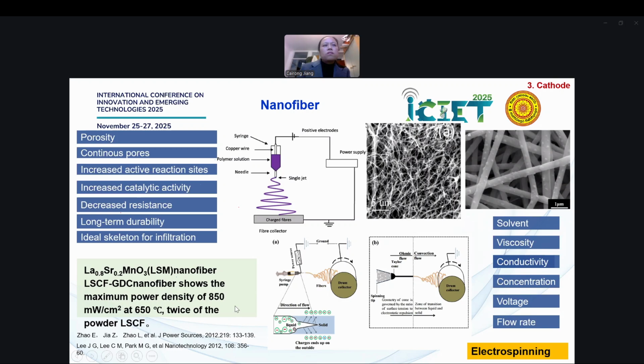And as reported in the literature, these two materials, lanthanum strontium manganese and lanthanum strontium cobalt iron, can be used at high temperatures for the first one, and the latter one is for 650 degrees. So it's a good choice that we have made. I've done a lot of research on the solvent, because the solvent does matter for what you can get. Sometimes you cannot even get a nanofiber at all if you don't have a good solvent. And the viscosity is also changed if you add some nitrate in.